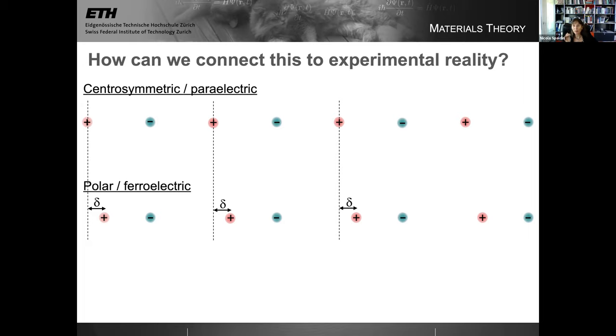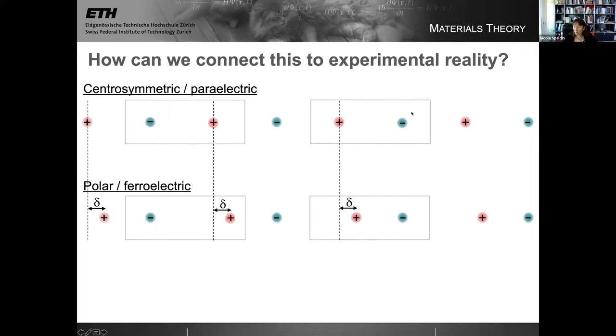If we compare these two, and look at how the polarization, the dipole moment per unit volume, changes between the centrosymmetric paraelectric and the polar ferroelectric structure, with this unit cell we see that the dipole has changed by a charge of plus one shifting to the right by delta. If we choose this unit cell, which started off with a different value for its dipole moment, again the change in polarization is a charge of plus one shifting to the right by a distance delta. So whichever unit cell we choose, whichever branch of the polarization lattice we're sitting on, whichever value we're taking of this many-valued quantity, we get the same answer for the change in polarization. The change in polarization is the electronic charge times the distance the cation is displaced, divided by V.